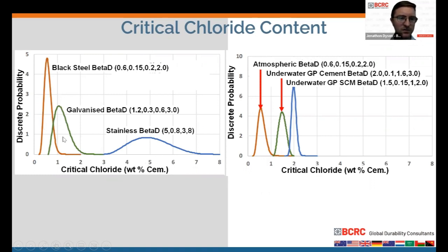It's also different in terms of the variable distribution. So in this case, the distribution for black steel is much narrower than the distribution for stainless steel. So a lot of times in modeling, we've assumed, and it's common practice in the industry to assume, a value of 0.4% by weight of cement. 0.4% of chloride ions by weight of cement is the value that will initiate reinforcement corrosion.